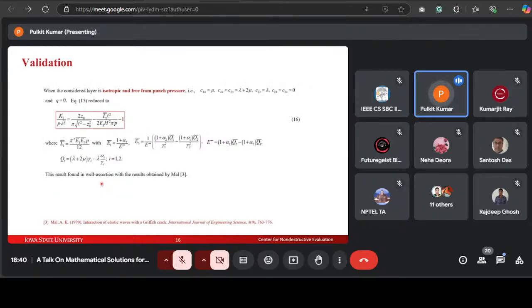When we reduce the elastic constants of the monoclinic material to the isotropic material, which is the easiest case, from 13 elastic constants to 2 elastic constants, and make it free from the punch pressure, the equation reduces to equation 16. This result is in good agreement with the result established by A. K. Mal for the isotropic case, which validates our mathematical model.